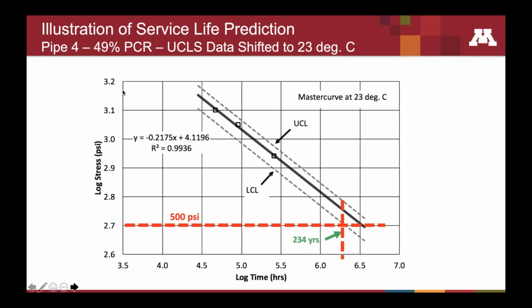And we did this for 9 different full-scale pipes and actually dozens of other materials that we evaluated. But for example, pipe 4 was manufactured with 49% post-consumer recycled material and at a service stress of 500 psi, which is again a very conservative assumption for stress in these pipes. We would predict that pipe to last in excess of 234 years.